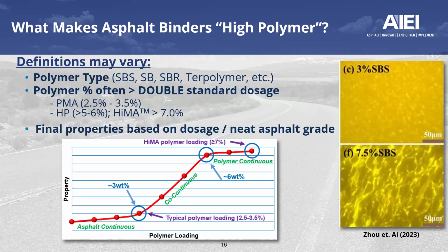Now, the major question is what makes an asphalt binder labeled as a high polymer? That definition may vary depending on several factors. The first one is the polymer type. The second one is the polymer content. A conventional polymer modified asphalt is typically modified with about 3% polymer content, plus or minus 0.5%. When we start pushing towards high polymer loading, we're talking about 5 or 6%. And in some cases, especially with proprietary products, we start talking about 7 and 7.5%.